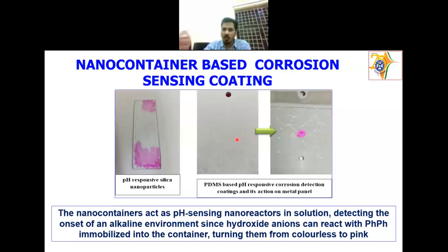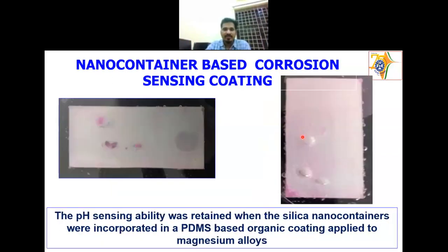Then again, we put a drop here. We found that where the drop is put, the color is changing. That means it is working when you are putting in the coating. And then we applied the same coating over a magnesium alloy.